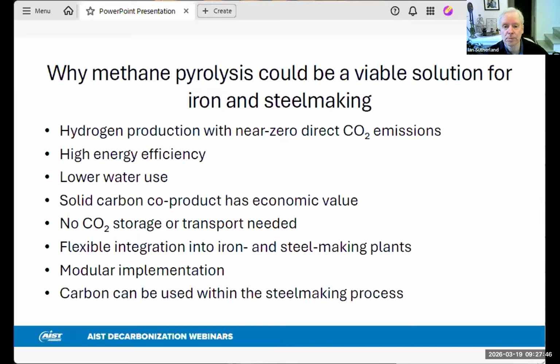Carbon black, which is the most basic carbon output of methane pyrolysis, currently has a market price of about $1,000 per ton. However, with further processing, the carbon can be turned into graphene, which can be used in EV batteries, or even into carbon nanotubes, which is a structural material. In these use cases, the market price can be up to $75,000 per ton for graphene and $300,000 per ton or more for carbon nanotubes. Although obviously in both cases, there will be the need for additional processing costs to take into account.